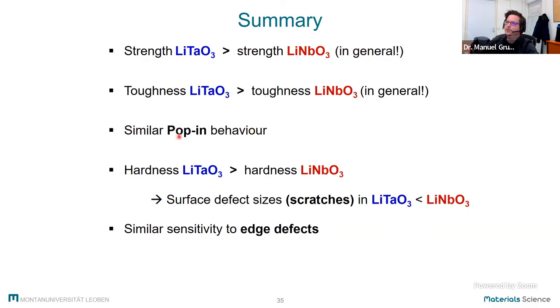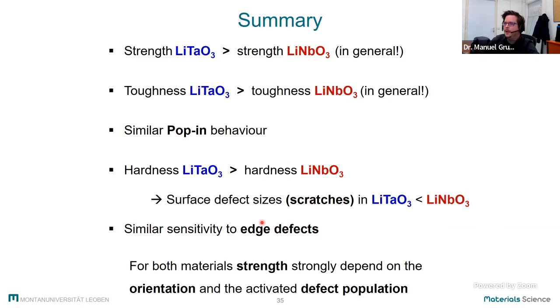We could observe a similar pop-in behavior leading to plastic deformation in similar directions for both materials. We could see a similar sensitivity due to edge defects. So this is important for the cutting processes of the wafers. And what I would like to highlight is that for both materials, we have to be aware that we have to strongly look at the orientation, our testing equipment and orientation, and the activated defect population.